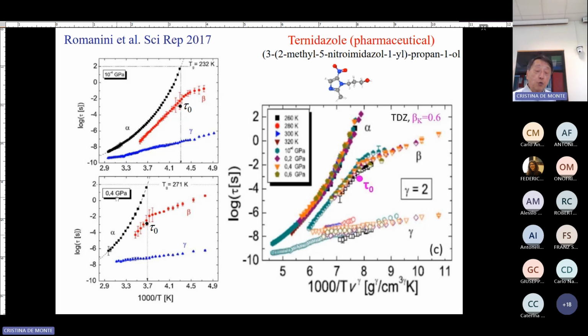Okay, so you do 0.4 gigapascal. You raise it by how many? Four orders of magnitude of pressure. You do the experiment with higher temperature. You also get the same good correspondence with tau 0. And that's the JG, and that's the alpha. Now, they know PVT, they know pressure, volume, and they transform this data in terms of this variable by a gamma, which they find 2 is the best, and they can scale everything together on the same plot with both of them having the same so-called T V gamma dependence. The dependence is different, of course, but they all depend on the same variable.